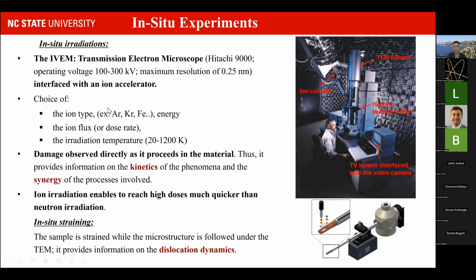accelerator, and we can choose the ion type and the ion flux. So we have control of the dose rate and the temperature; we can cool down or heat. And the beauty of the technique is that we can observe the microstructure using the electron beam as it is being damaged by the ion beam during the process. That way we can get kinetics information, but also a picture of the spatial distribution of defects created and how they interact with the surrounding features.